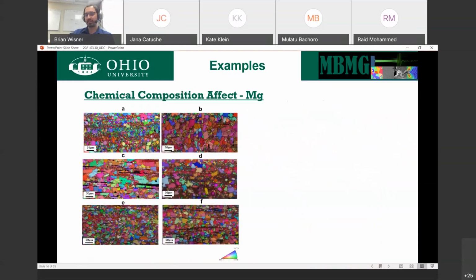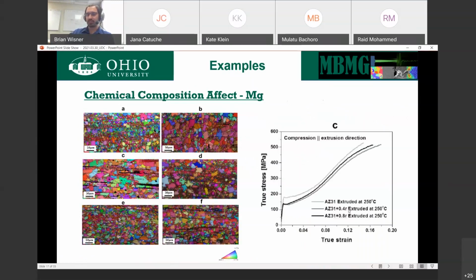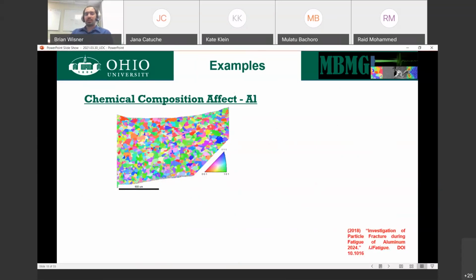We can also affect its composition by adding to magnesium. In this case, we're going to go with an alloy of AZ31, and we're going to add additional elements in order to change the microstructure again to produce different results. Notice, though, that by adding and altering the elements with very small amounts, we're not drastically changing the mechanical behavior. Not nearly as much as the orientation was in this case. We can do the same kind of a thing looking at a different alloy.